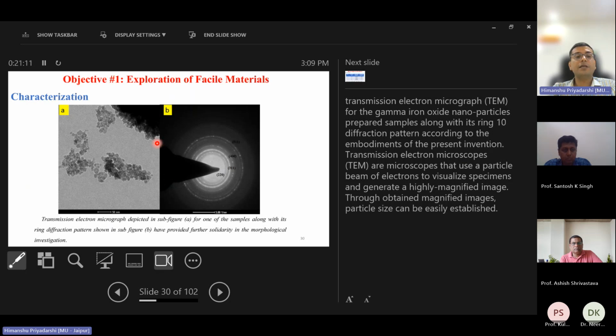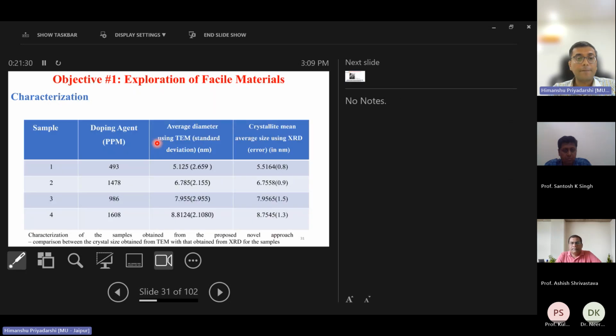Now these are the transmission electron microscopy results. Why do we go for transmission electron microscopy? It gives us more conviction regarding the formation, the size and the fidelity of the materials which is found. Using TEM, if we make a comparison, the crystallite size which was found using Scherrer's formula was 5.5 nanometer with an error of 0.8, and using transmission electron microscopy it was 5.125. They are nearly in agreement with each other.